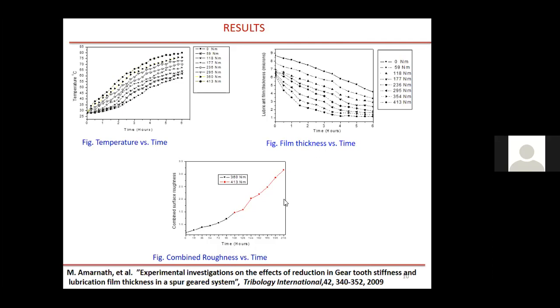With respect to the increase in load, lubricant film temperature is also increasing and film thickness is decreasing in this fashion. Then, because we have conducted accelerated test conditions, accelerated in the sense it is more than 3 to 5 times the allowable load condition, it is called an accelerated test condition. Overloading the gearbox or operating under overspeed is called an accelerated test condition. Since we have conducted experiments using accelerated test conditions, the surface roughness has increased in this fashion.